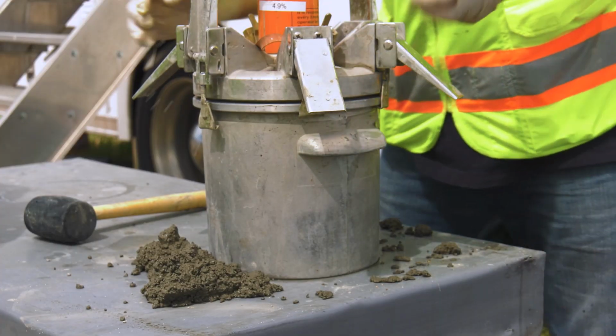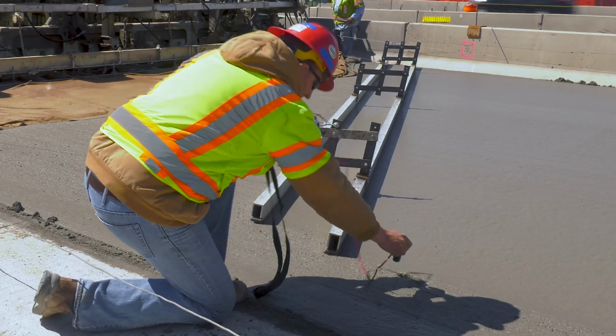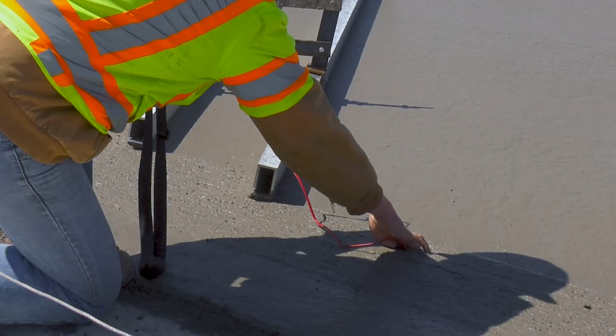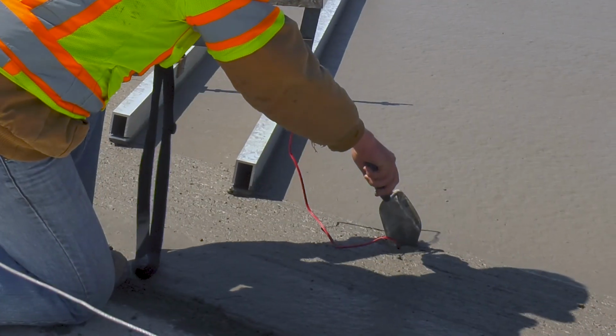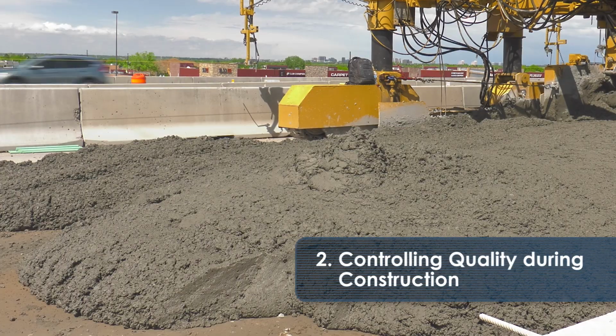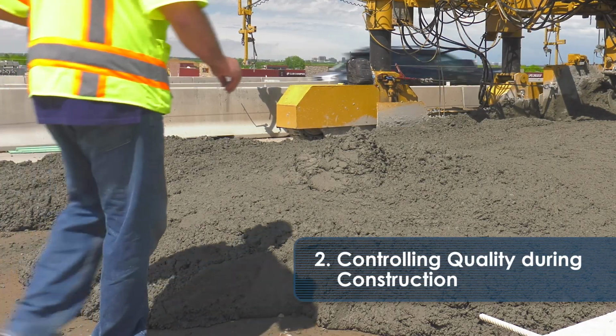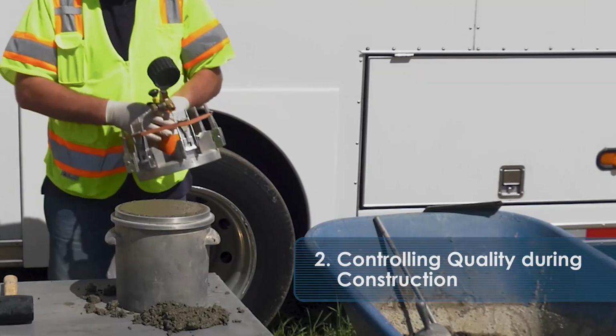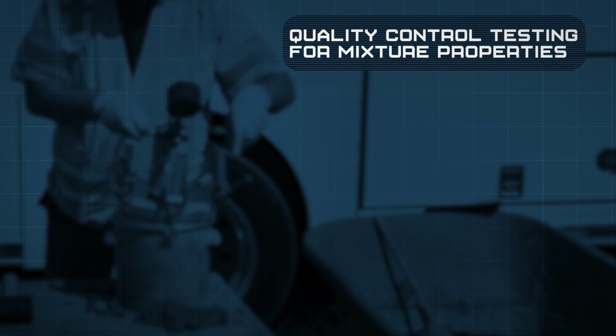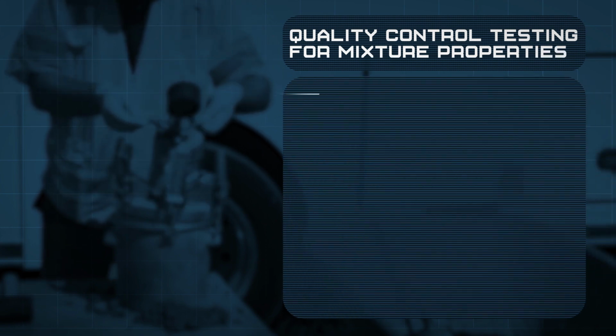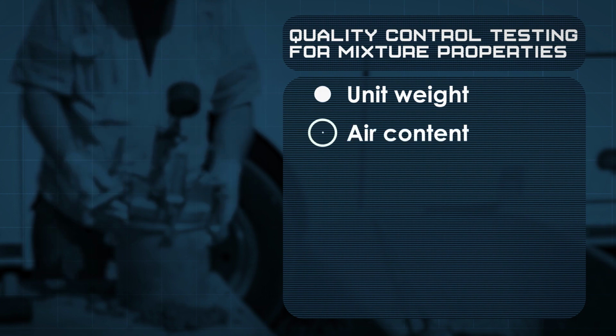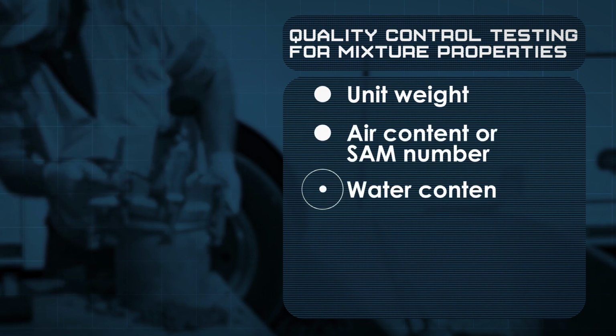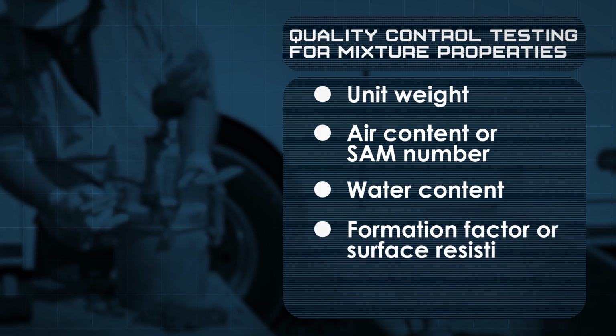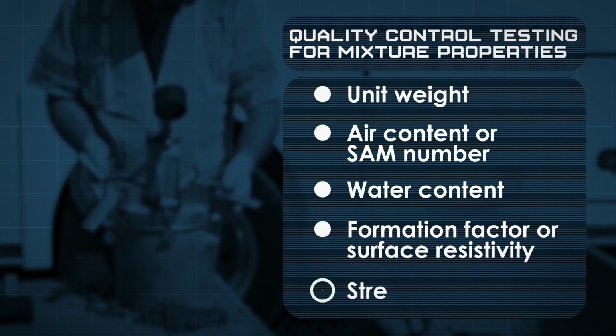In a performance-driven quality assurance specification, the burden is on the contractor to deliver the concrete mixtures as specified by the agency. As such, the contractor's quality control process plays a key role in ensuring quality of the concrete mixtures. Agencies should require contractors to provide and adhere to an approved quality control plan, which includes quality control testing during construction to monitor and control quality for mixture properties such as unit weight, air content or SAM number, water content, formation factor or surface resistivity, and strength.